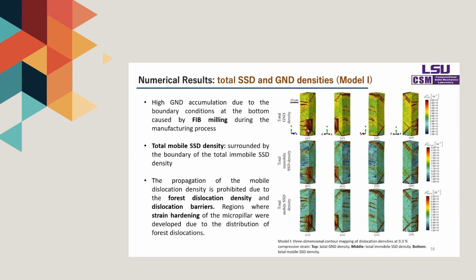Comparing the total SSD with the total immobile SSD density, the total mobile dislocation density is distributed inside based on the boundary of the total immobile SSD density. The propagation of the mobile dislocation densities is significantly reduced due to the forest dislocation density in terms of the accumulation of GND.